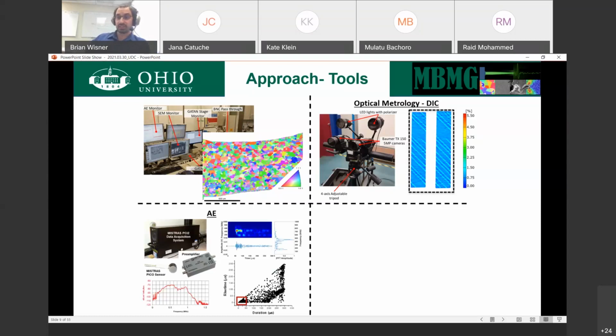The second method I use a lot is acoustic emission. And this one you will see I use the most. There's a reason for this. DIC is powerful. It gives us a lot of useful information, but you can only see a surface. So if the damage isn't happening on the surface, or at least near enough that it affects the surface, you're not really going to see a change in your DIC results.